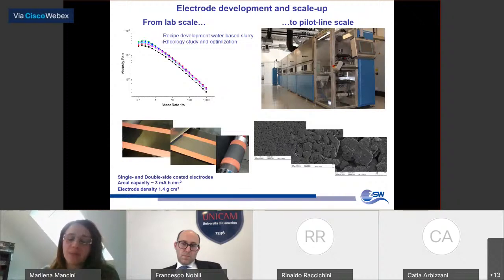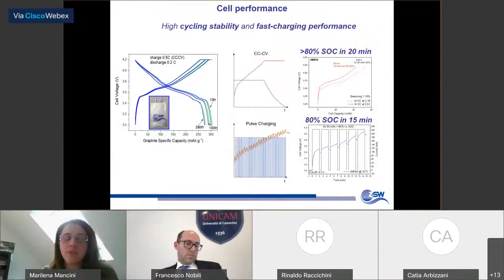So we have extended the processing of the materials from lab scale to pilot line scale to have larger electrodes and be able to test the electrodes in full cells versus NMC. And here you can see a short overview of the results, and graphites produced with tailored parameters during the spheroidization can be directly used in the cell by offering good cycling stability, and by tailoring also the charging procedure, it was possible to reach 80% of state of charge within 15 minutes, which was the final goal of the project.